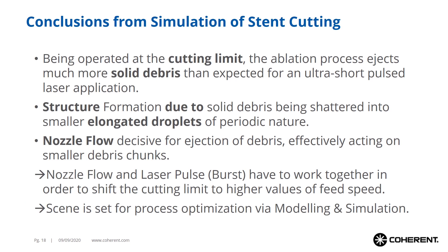The simulation also explains the feather-like structures of debris formed on the cutting edge. Still pictures from the video show more clearly that the separation of debris into smaller elongated droplets is responsible for these feather-like structures. Looking at the standard nozzle flow, there is not enough time for it to act upon the heavy debris. The conclusions from the stent cutting simulation are: the cutting limit manifests in almost solid debris from the cutting front, which is difficult to eject above a certain speed — quite unexpected for an ultra-short pulse process. The mystery of structures on the cutting edge is explained by the shattering of debris into smaller elongated droplets. Most importantly, the nozzle flow effectively acts only on smaller debris chunks, setting the scene for further process optimization.